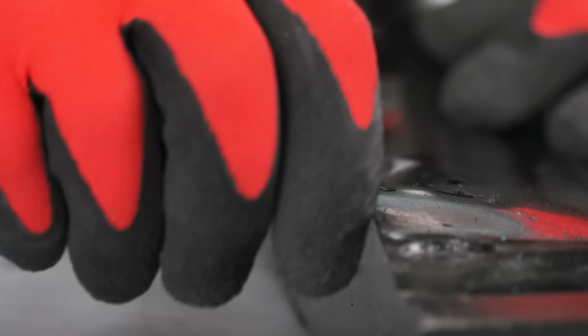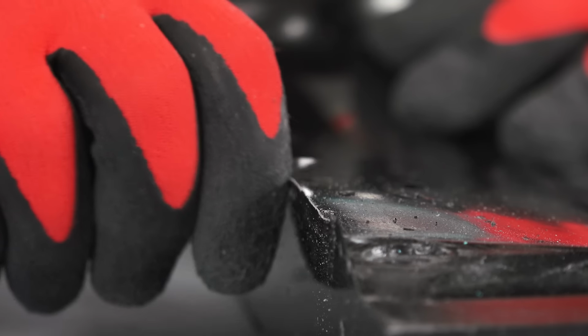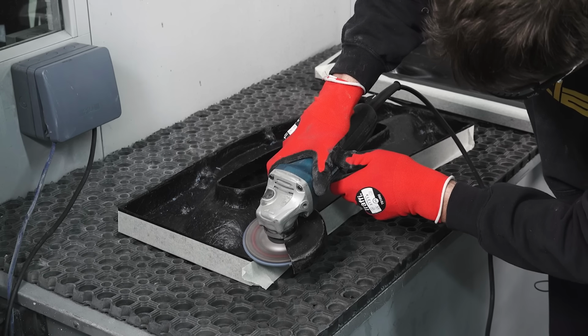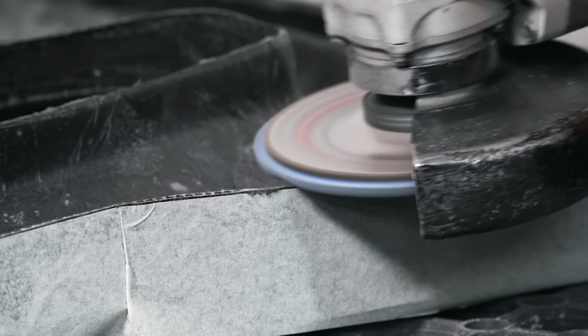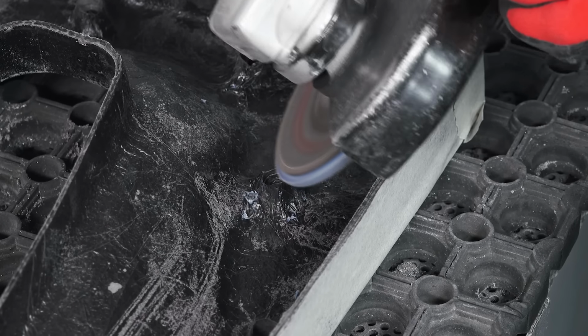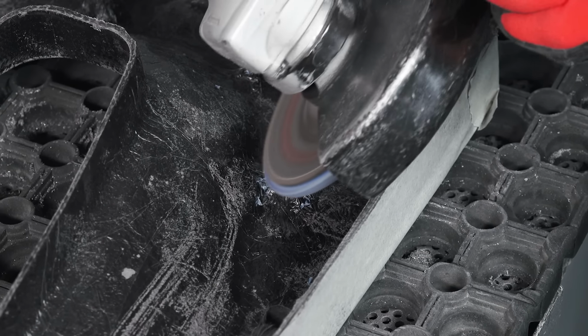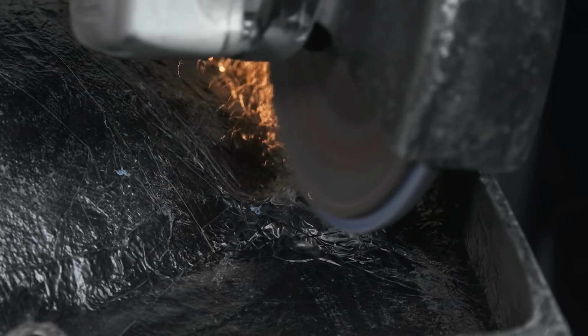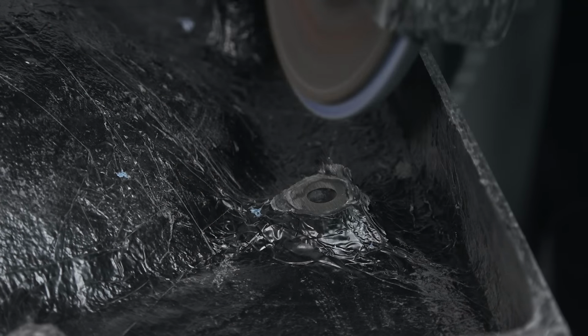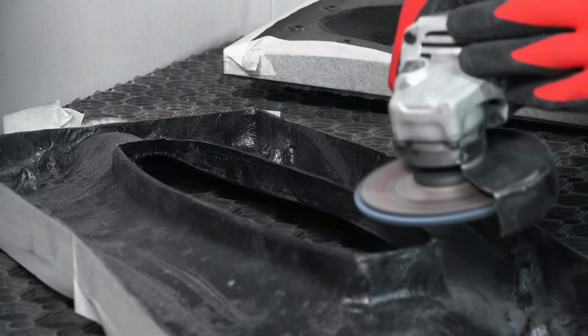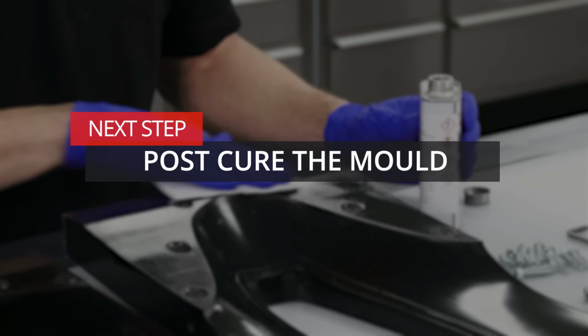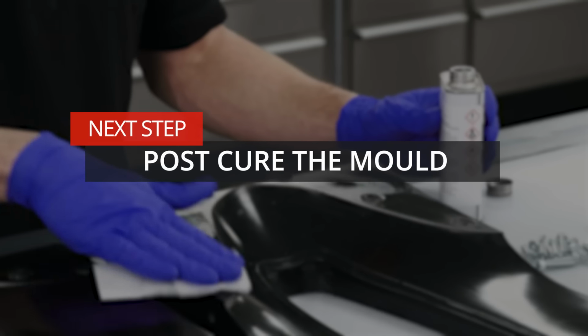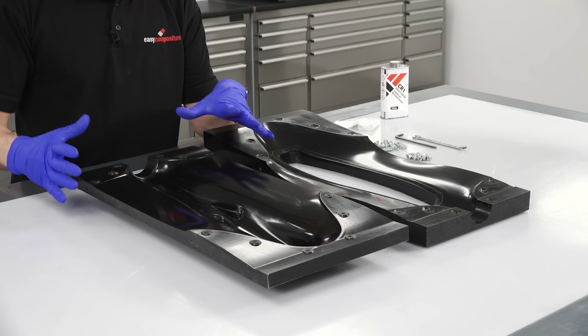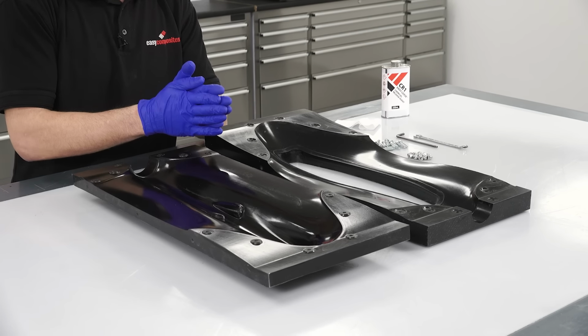The flashing is then removed from the flanges. The flanges are trimmed and the material around the clamping bushes is ground flush with the top of the bush. Doing this is necessary both to provide a flat surface to bolt against and also to remove any sharp flashes which could potentially burst a bag when the mould is used. These are the moulds as released from the patterns. I'm really pleased with what we've got at this stage.